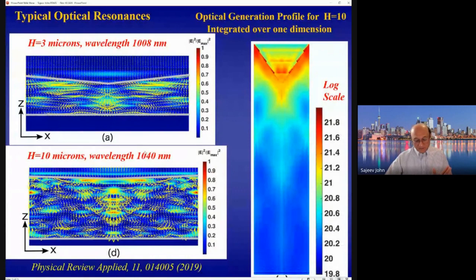What is important for solar energy and the efficiency of the solar cell is integrating over all the wavelengths associated with these different resonances and creating what's called an optical generation profile. That's shown on the right. So this is the total density of electron-hole pairs that is being created per unit time within a 10 micron thick solar cell with an inverted pyramid at the top, showing just one unit cell. This is in a logarithmic scale, so 21 refers to 10 raised to the power 21 per cubic centimeter photogenerated carriers. So quite a lot of the photogeneration occurs near the top of the cell, and then still a fair amount towards the bottom of the cell, where this number goes down to 10 raised to the power of 20.